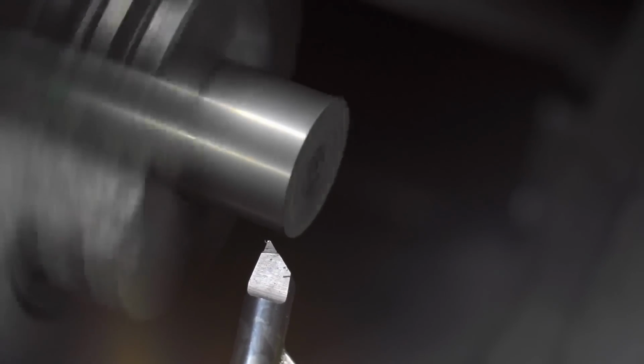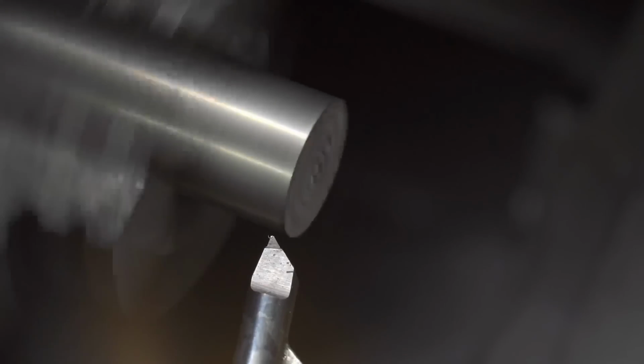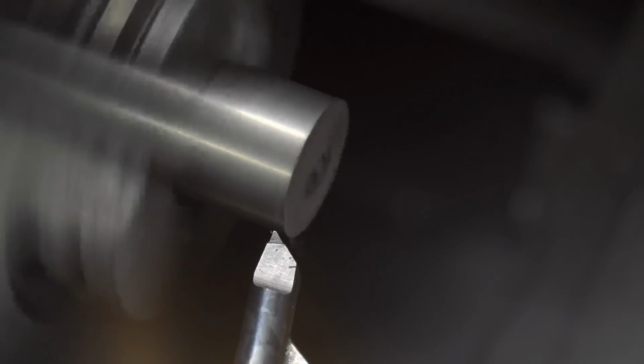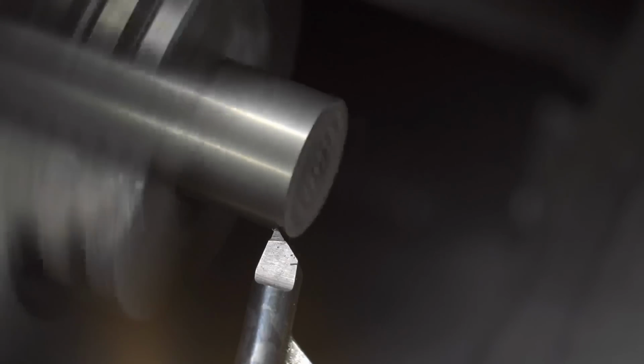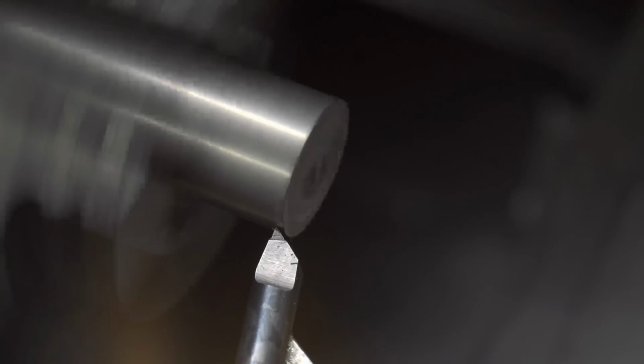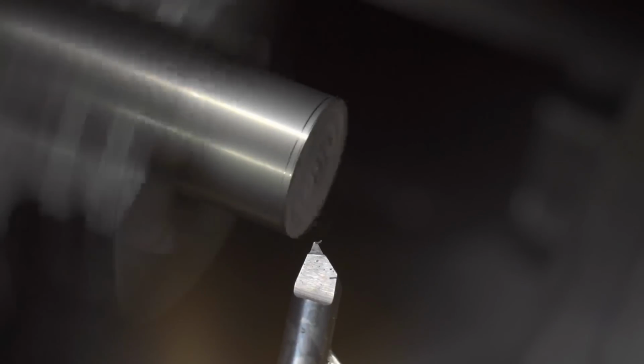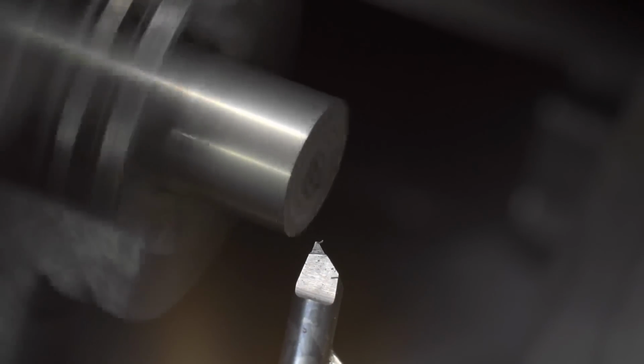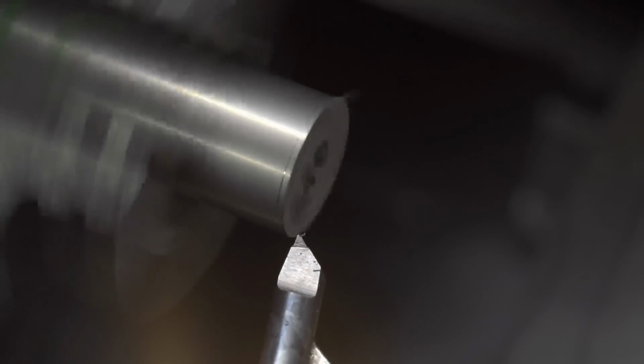To test the carbide tool, I have some 316 stainless steel. The purpose of this tool is to be able to take a very small cut and still leave a good finish. The first cut is 0.2 millimeters, the second cut is 0.05 millimeters, and the third is 0.02 millimeters, about 1/1000th of an inch.